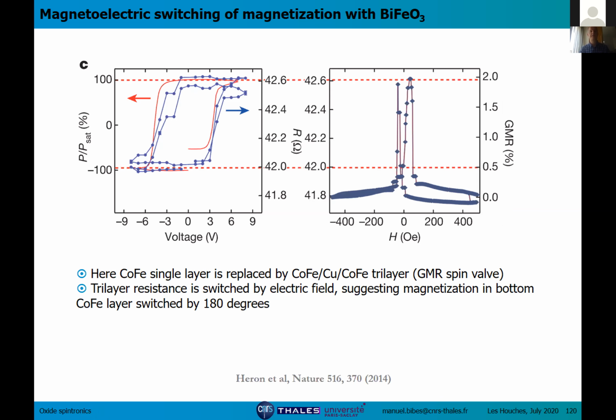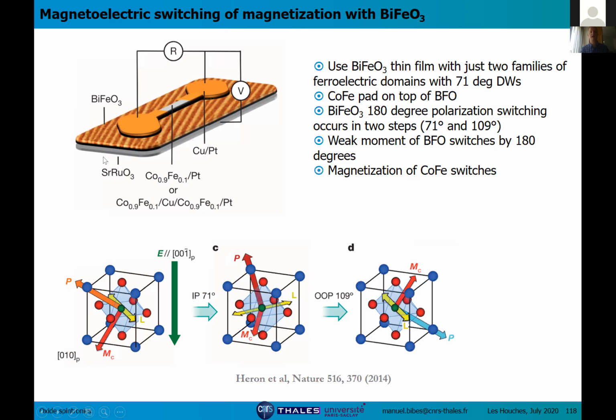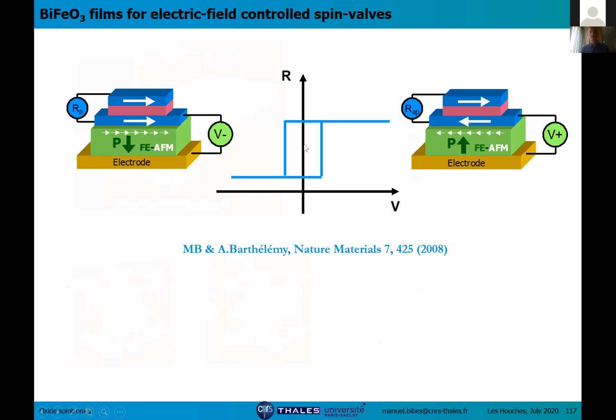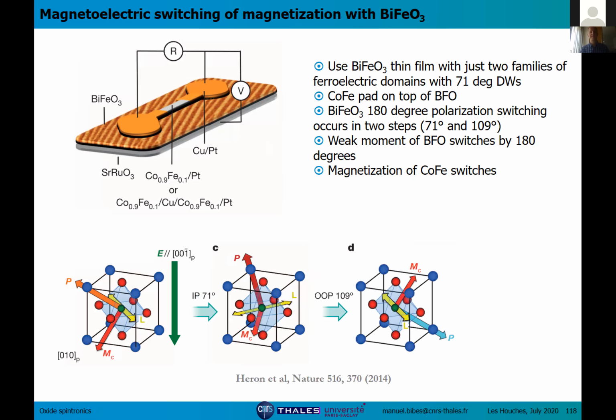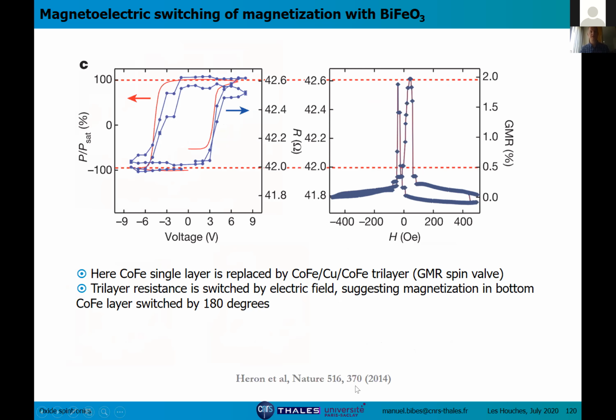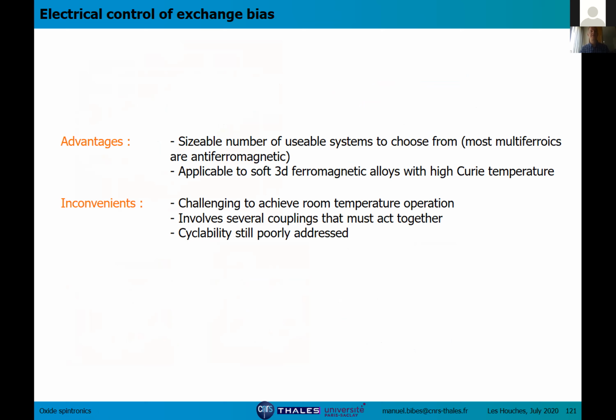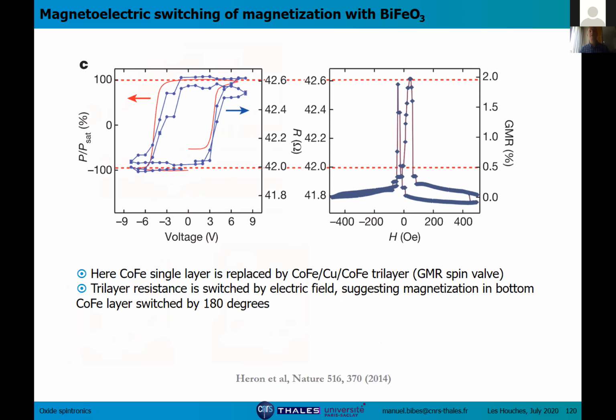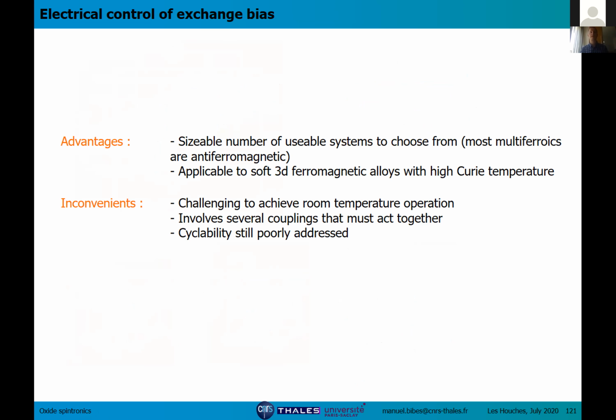And this is the GMR curve of the cobalt iron copper cobalt iron trilayer, and this is the resistance of the trilayer as a function of the voltage, and you see that they are able to achieve an almost complete switching of the resistance with voltage that mimics the sketch that I had here in this device that was proposed more than 10 years ago. So this was published 6 years ago in Nature, and there's a lot of room for improvement still, in particular as regarding endurance, because if you want to make a device out of this, you need to have endurance up to millions and maybe billions of cycles.